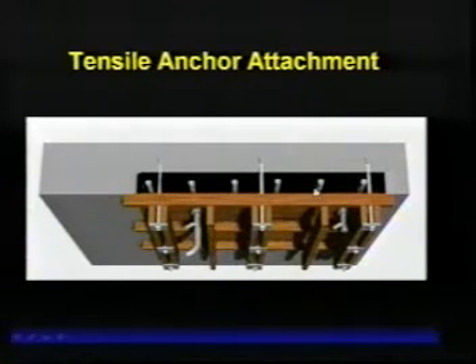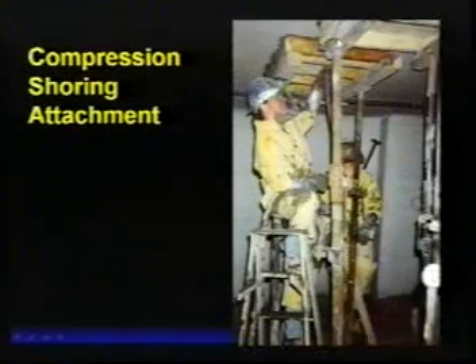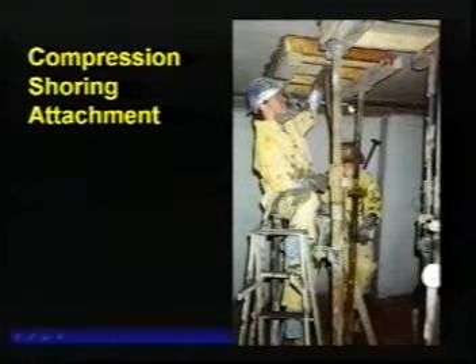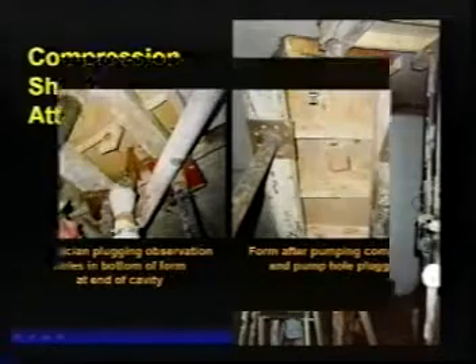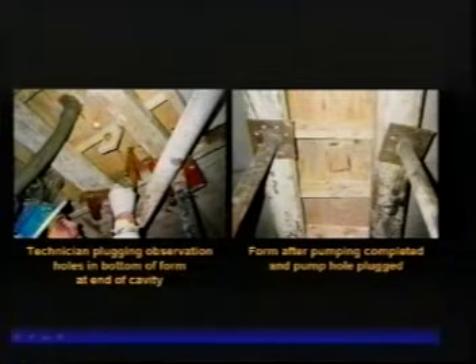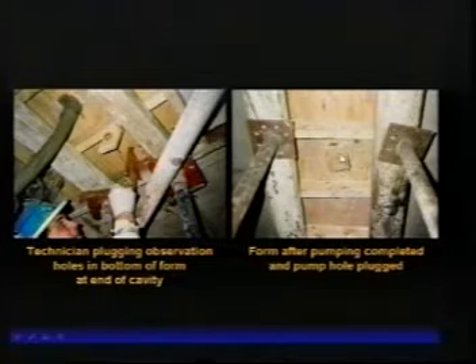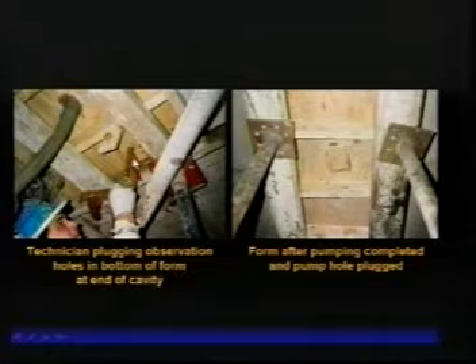The way these formworks are attached to the existing substrate is either through a tensile anchor like this, or through a compression anchor using, in this particular case of overhead repairs, simply some shore posts. The shore posts are screwed tight, so that basically, there are very small repairs beneath these forms, and the pressure that develops is reacted against these shore posts. These are just showing some different attachments and different locations. These are the port locations, and these are some very low-tech valving made from the hole saw that cuts the holes. They're nailed to these pieces of plywood, and as the hoses are removed, these are slid over to seal those locations.